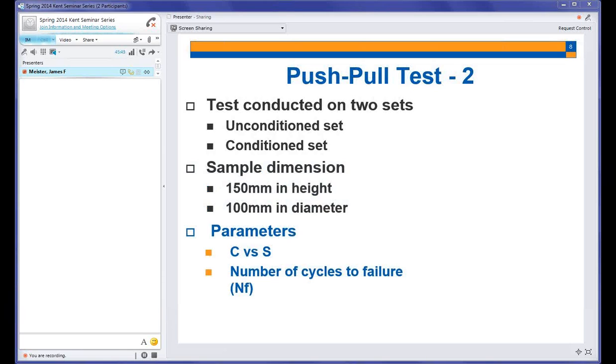Pseudo stiffness is basically the amount of drop of the complex modulus at each loading cycle compared to the initial complex modulus that we started the test with. And that's why we use the complex modulus. We need the initial value of the complex modulus. That's why we need to run the complex modulus before we test the sample for the push-pull test. And also the second important thing, the number of cycles to failure. This is a fatigue test, so we need to know the number of cycles to failure, as we get this parameter from any fatigue test.